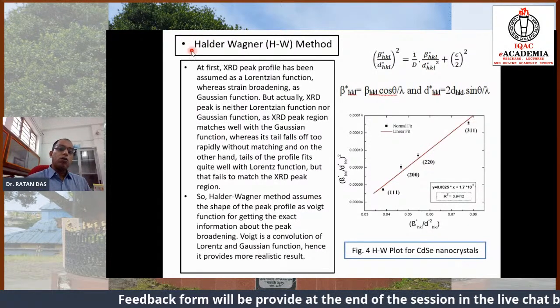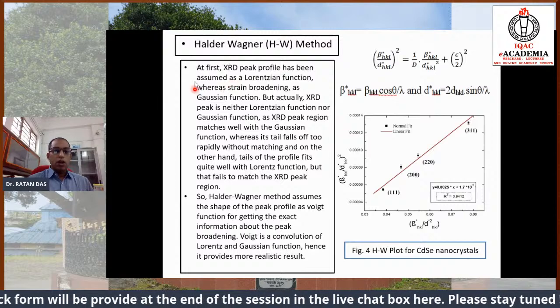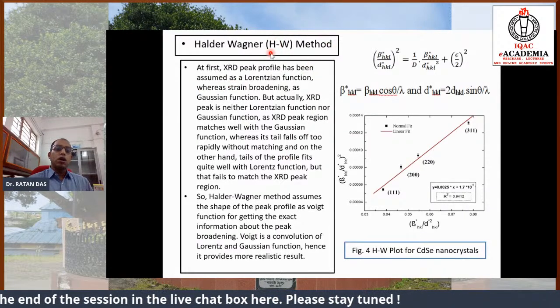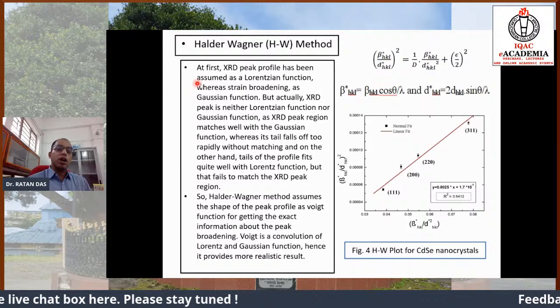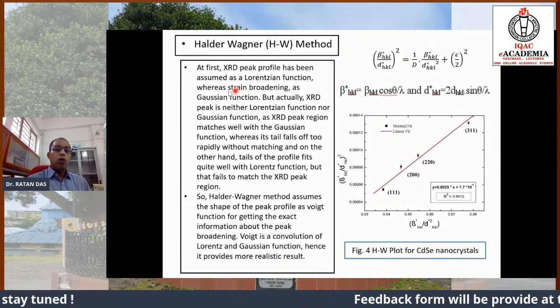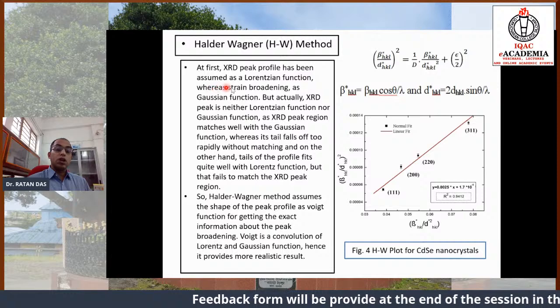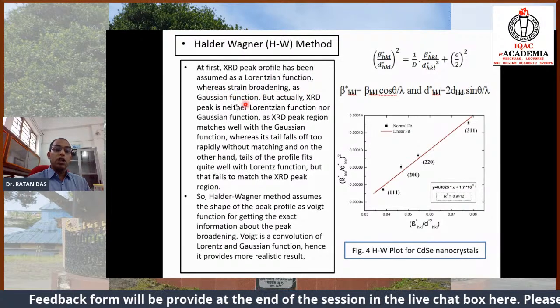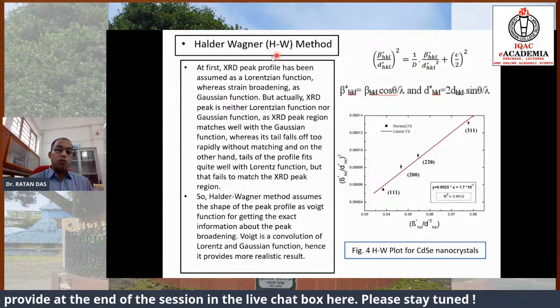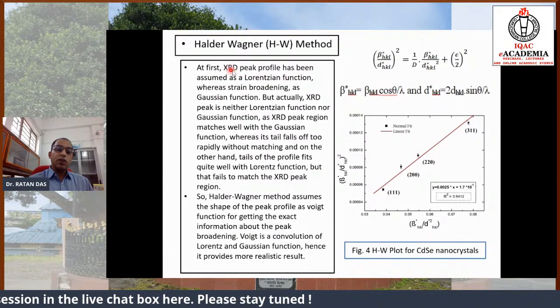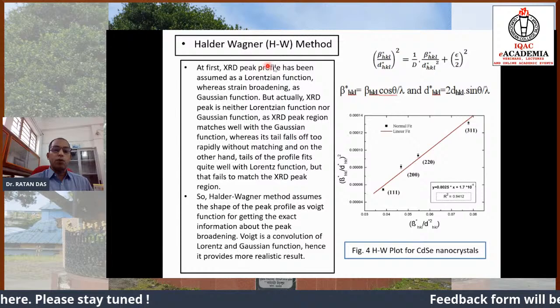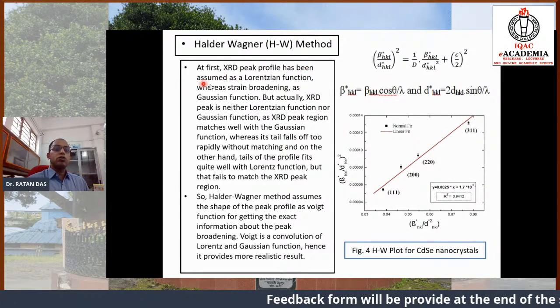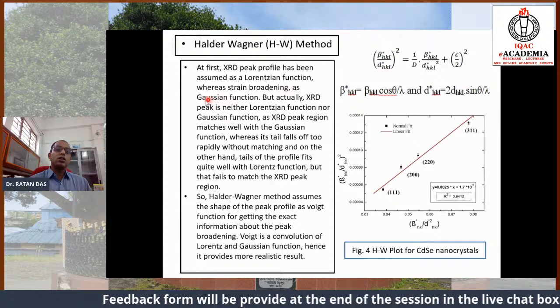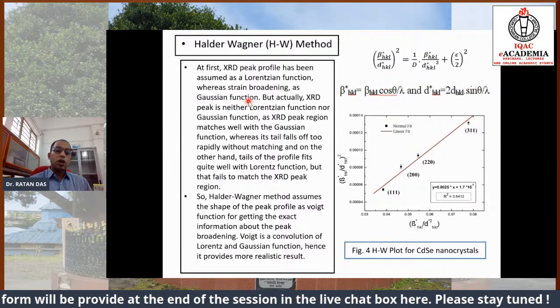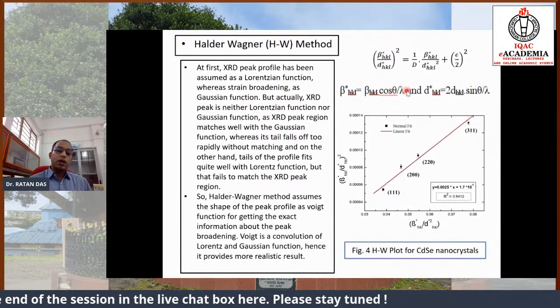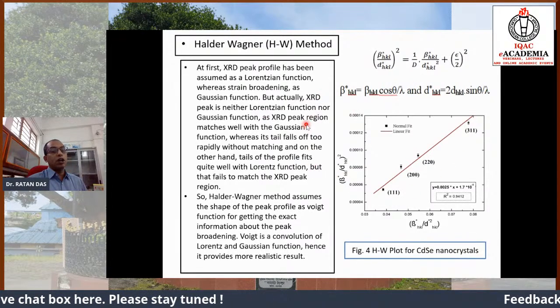Now, another method is the Halder-Wagner method. In this method, the exact peak profile is assumed to be a Lorentzian function, whereas the strain broadening is a Gaussian function. Size has been assumed as a Lorentzian function, and strain broadening as a Gaussian function. But the XRD peak is neither purely Lorentzian nor Gaussian.